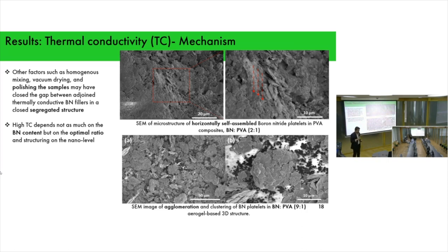When you compare the SEM structure of boron nitride to PVA at a 2 to 1 ratio with a 9 to 1 ratio, we see that in the 9 to 1 ratio, you see a lot of agglomeration, clustering, and entanglement of BN nanoplatelets. As we discussed in the thesis, it shows some brittle behavior. Hence, we can conclude that high thermal conductivity does not depend only on the BN content, but on the optimal ratio and the structuring on the nano-level.